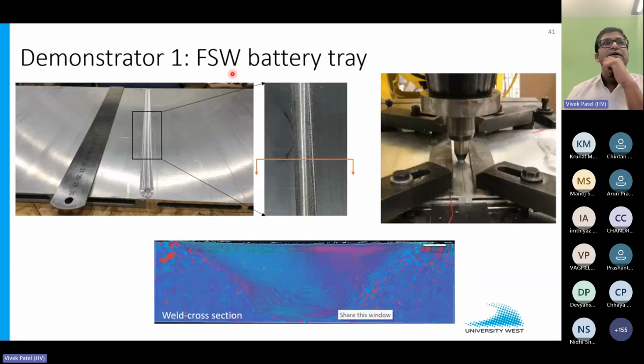Then you see this is the real battery floor panel, and this is the cross section of the weld. In this color metallography, you can see these bands in the weld nugget itself. These bands represent the typical onion structure of friction stir welding. We see that the material flow is happening at such a high speed, and there is a lot more to understand and learn from these onion bands in the weld nugget.